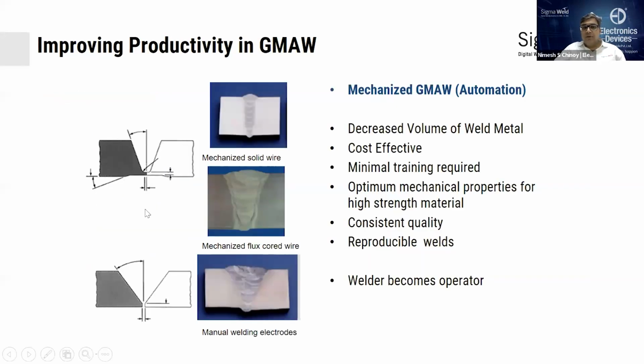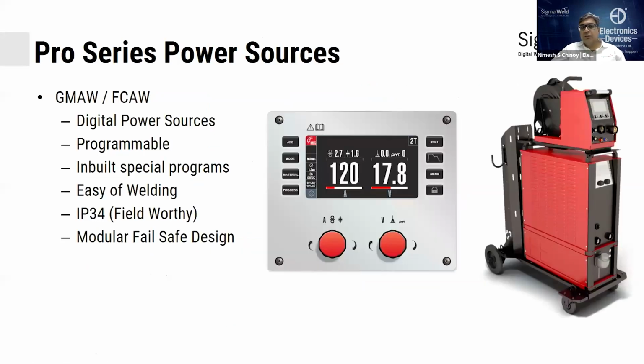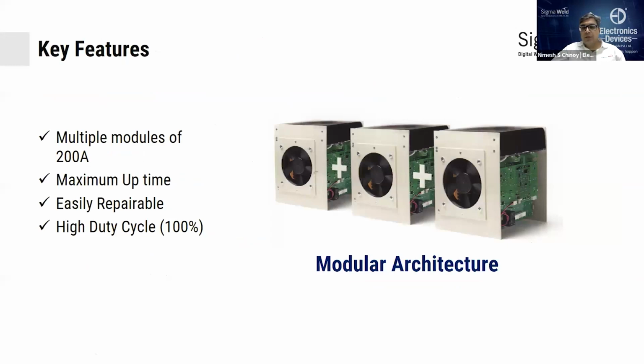If you look at this productivity improvement from normal GMAW to mechanized, this is the normal GMAW, bigger V, and when you move to mechanized, you can see single pass per layer, and therefore much less material required to weld. At the same time, there is better strength of the geometry. These are the high-end power sources called Pro Series, which are modular in nature. Each one of them is only 200 amps. You can keep adding to build up your capacity.